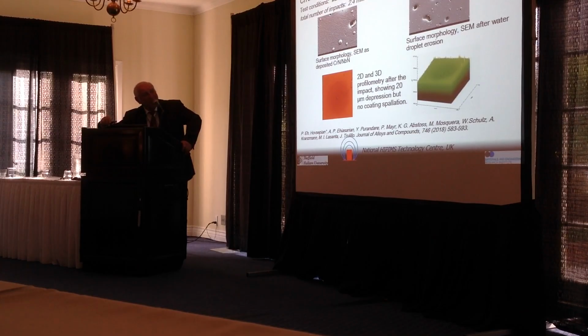And this velocity is proportional to the toughness of your material. And in recent years, there was very fine research which demonstrated that the toughness, like the hardness of the material with the nanoscale multilayer structures, in fact is also improving and increasing in the specific range. So these are really very tough materials. And if you don't believe the equations, that is how the surface looks like after such a droplet attack. You have just polishing effect. We have formed a crater here, a dimple, 20 micron deep, and the coating is still intact.